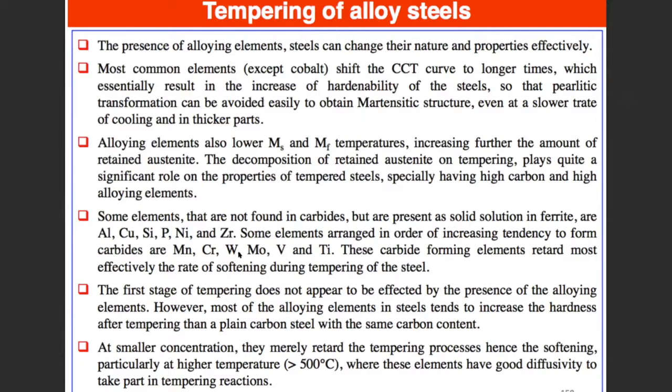You can imagine what happens if we simultaneously diffuse the carbon out of the martensite, but then we also nucleate nearly homogeneously a fine dispersion of carbides, right? Which are very potent strengtheners. Right? So everything gets tied together, and we have to think about all of these different effects together.